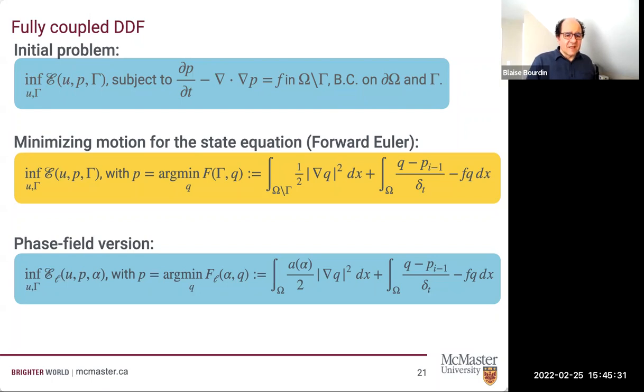The difficulty with that is, you now have to couple this minimization problem with the parabolic evolution, and all the tools that we use for the study of the fracture problem come from the calculus of variations. So the very natural way is to reformulate your parabolic equation in terms of a minimizing motion. So you discretize forward in time, and you interpret the discrete problem as the Euler-Lagrange equation for a minimization problem. And now you end up with a bilevel minimization problem: inf of E of U, P, and gamma, subject to the fact that P is itself the solution of a minimization problem.